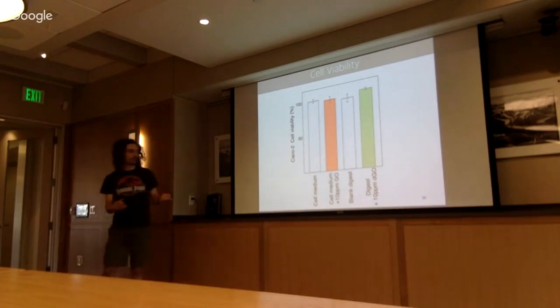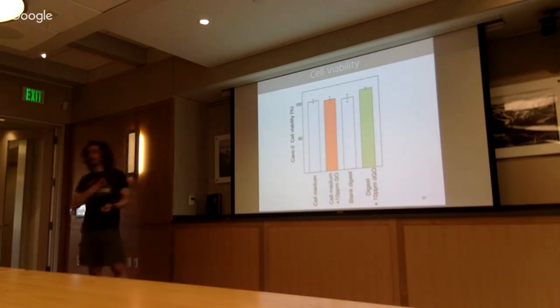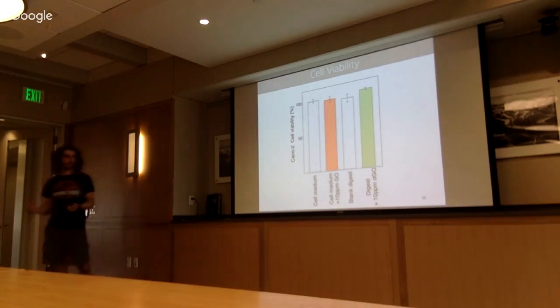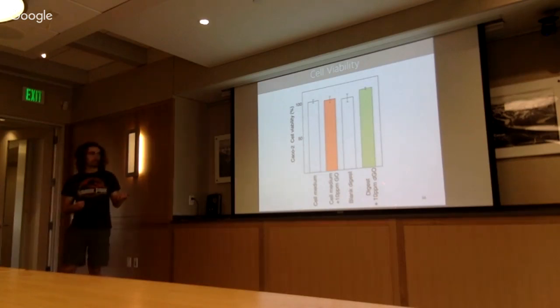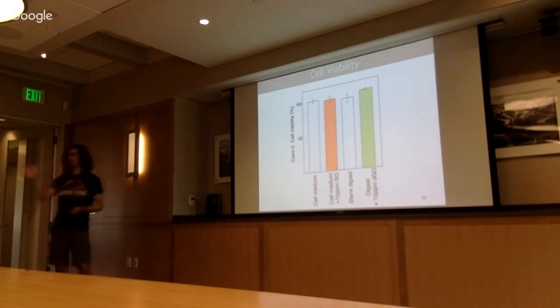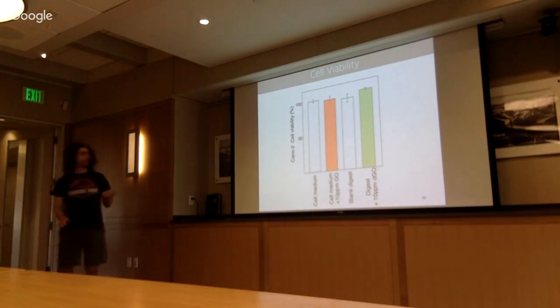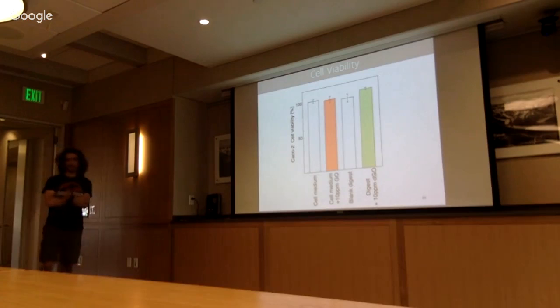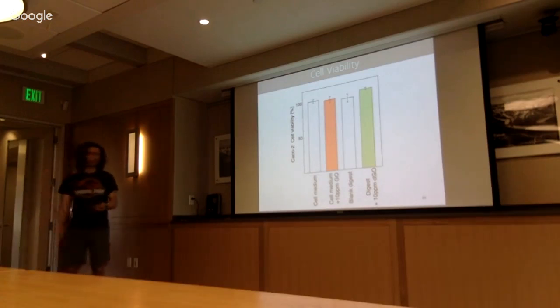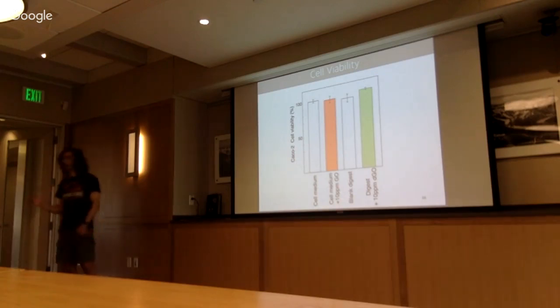Also, we took the digest, so what is coming out from this GI tract simulator, always with 10 ppm of the GO that has gone through all these three environments. And even here, we didn't see any toxicity. Again, this is a preliminary result because we're checking just one cell culture, and just one concentration, even if it's really high.